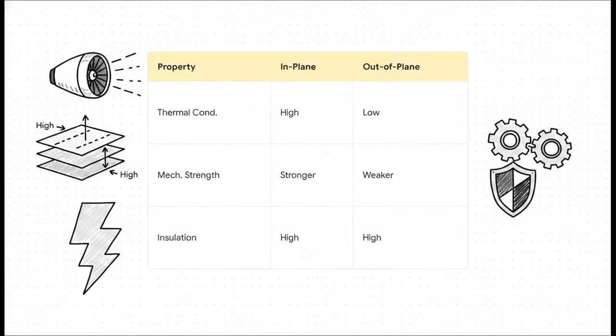But we've got to come back to that anisotropy. The highly directional nature of HBN means you have to orient the material perfectly within your hardware. Notice the thermal conductivity difference here. It's super high along the in-plane layers, but incredibly low, just 20 to 25 watts per meter Kelvin, perpendicular to them. But the real magic is the electrical insulation. That stays incredibly high, over 10 to the 14th ohm centimeters in both directions. So think about that. It conducts heat like a metal, but insulates electricity like a premium ceramic.